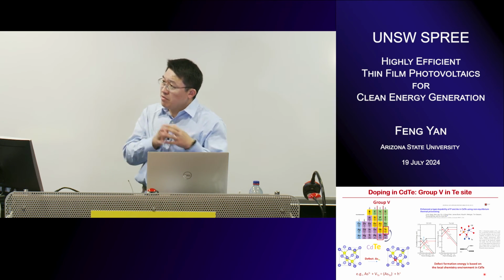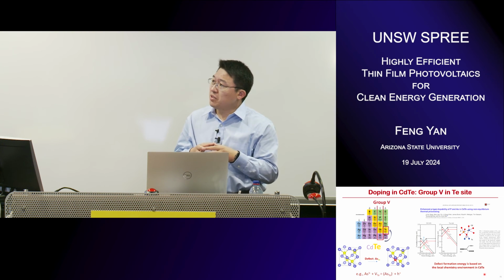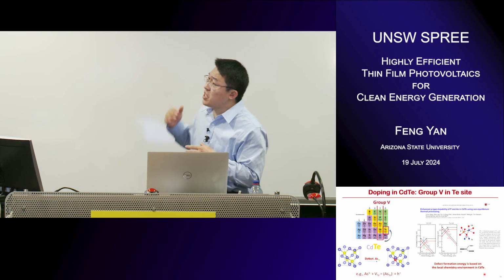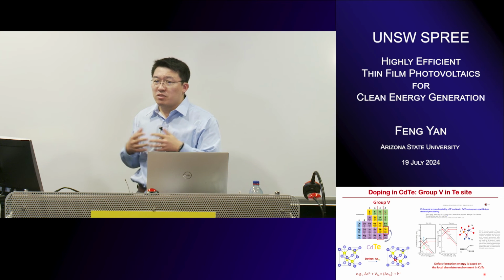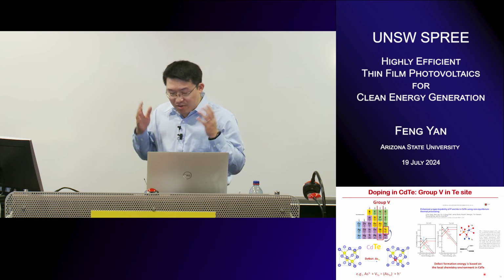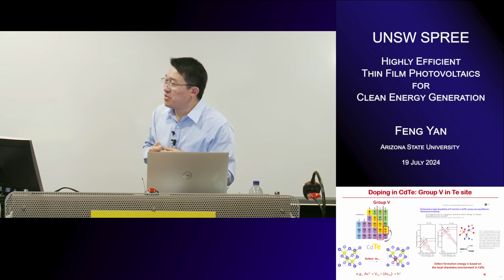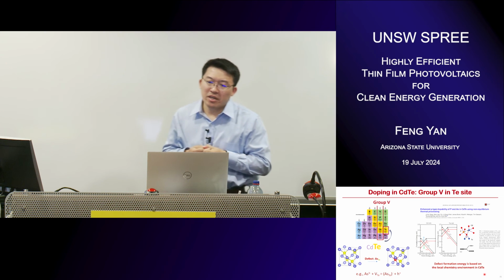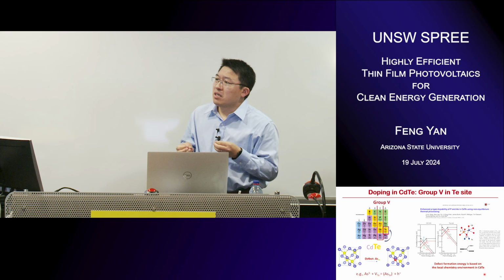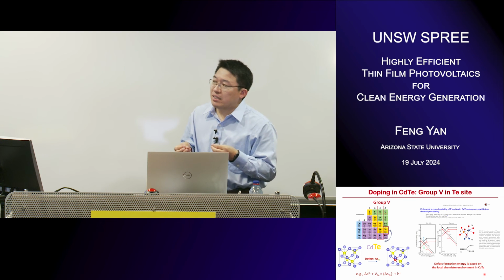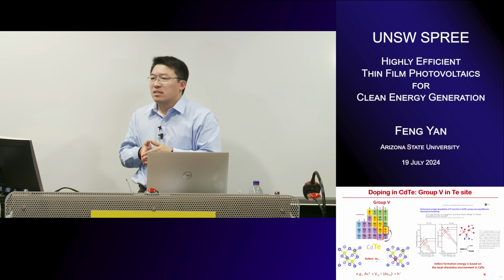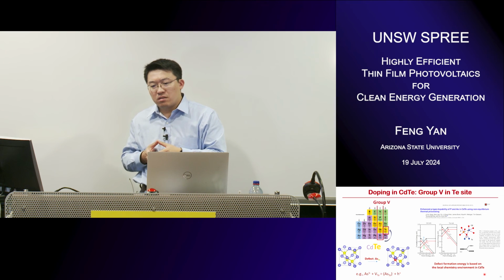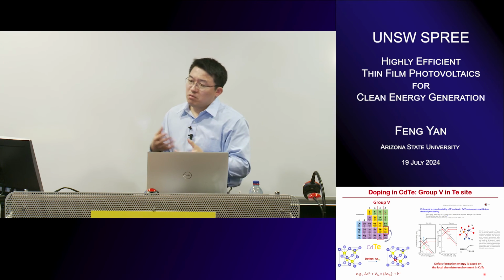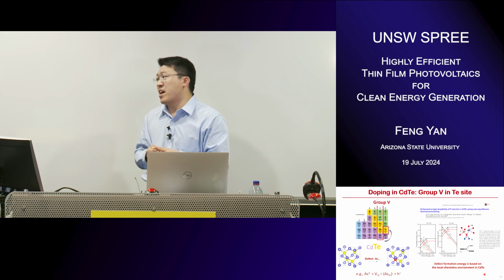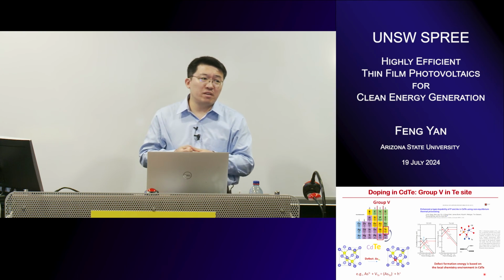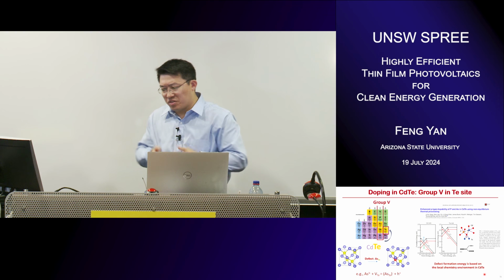We can see that before and after the cadmium chloride treatment, the carrier lifetime can jump significantly, one or two orders of magnitude. And from the chemistry side, like what I mentioned, with chlorine, we can see the defects and chlorine segregation. There is DFT calculation. Chlorine also acts as N-type doping. It's significant if you check the element distribution.